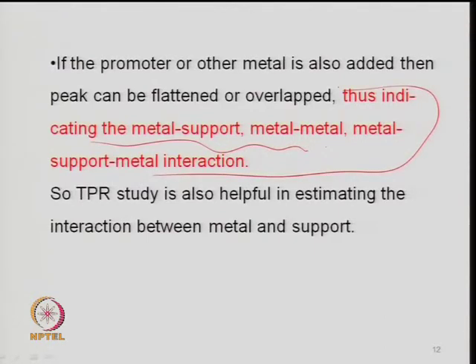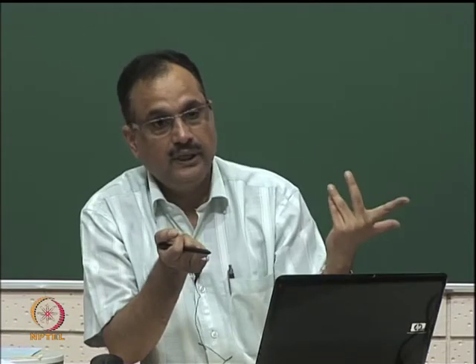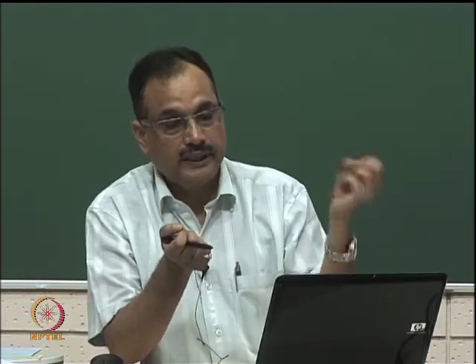If there is a promoter, it may also interfere with the reduction temperature. The reduction temperature may change in the presence of a promoter because adding it may improve dispersion. If crystal sizes are smaller they react faster — that is the essence of nanocatalysis. Reducing the size can change chemical structure and shape, making reducibility easier. Promoters can improve dispersion or can have negative effects. Through TPR you can get information on metal-metal interaction and metal-support interaction, which are important for understanding the catalyst properties.